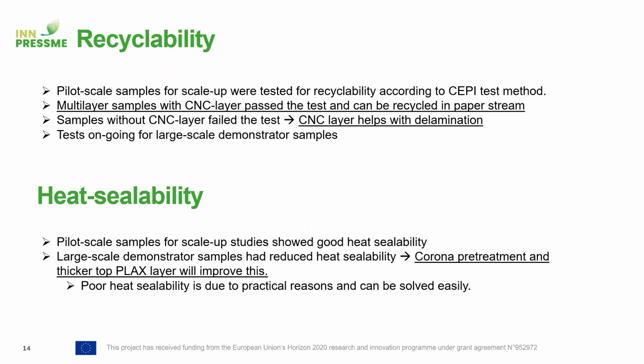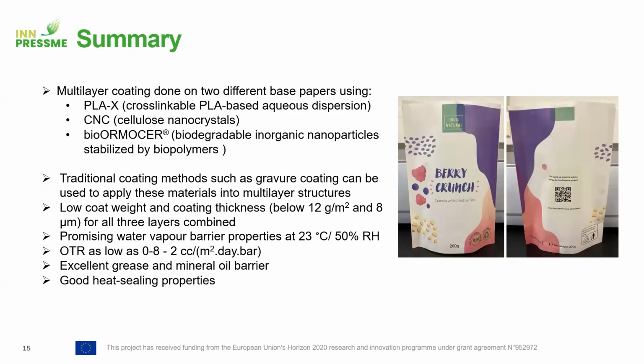We tested the recyclability as well, and we saw that when we have the CNCs there, it enhances the recyclability because it serves as a dispersing agent and helps with the delamination. Unfortunately, the samples without the CNC did not pass the test, but the tests are still ongoing for these large-scale industrial demonstrators. Heat sealability was achieved with the PLAX, and we got good heat sealability. With the large-scale demonstrator, heat sealability was slightly reduced because there were slight problems with the corona pre-treatment, but we can change this and also apply a thicker PLAX layer to have good heat sealability at industrial scale.